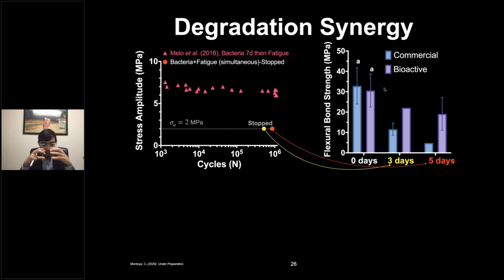But if you do a synergy test, 3 and 5 days cyclic load under these bacteria attacks, there is a drop on the bond strength of the commercial. We went from 30 down to 10, 15 megapascal strength on the commercial, and not as much on the bioactive, which has the antibacterial, piezoelectric fillers.